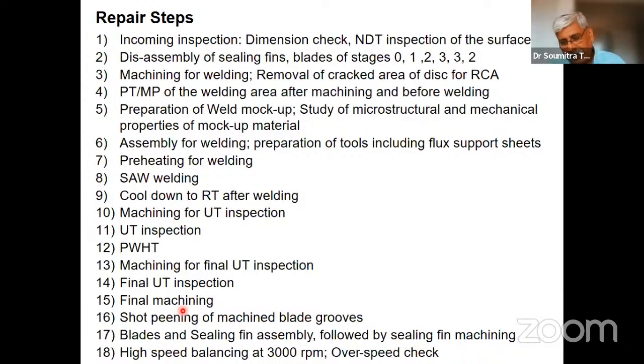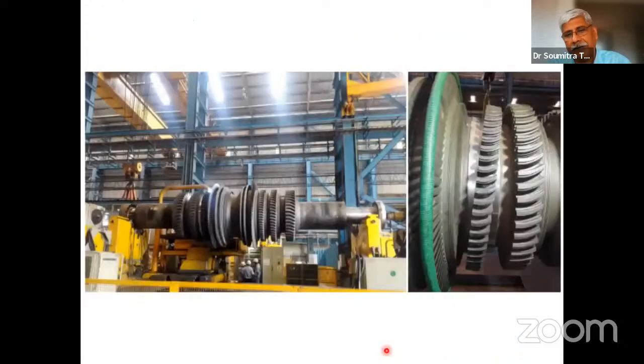Not the whole disc, but only a small part of the disc where the repair was there. And we took special care to ensure that the microstructure that was produced was all right to survive the type of conditions that would be there during service. So after all that, the blades were again assembled, sealed, high-speed balancing was done, overspeed checking was done, and this rotor was taken back by the owner for reuse, and it has been used again. So this was repair and refurbishment. And I think it's not very different to what we are talking about in remanufacturing.